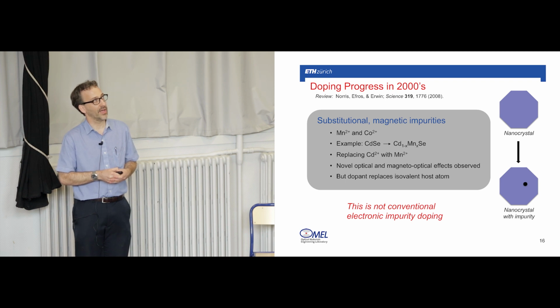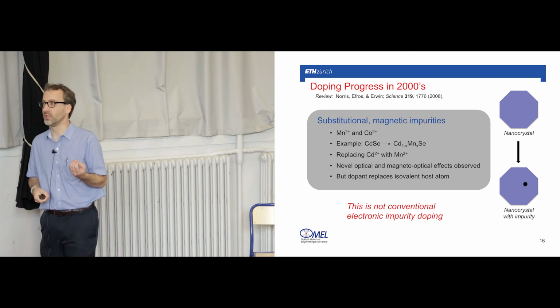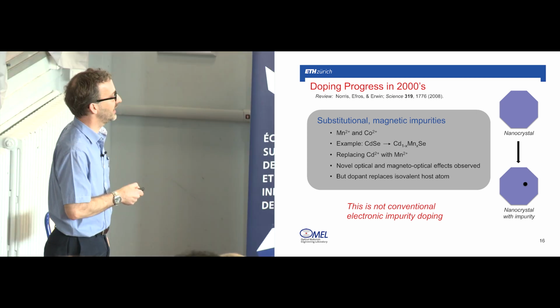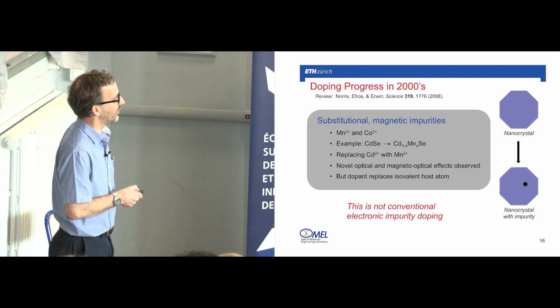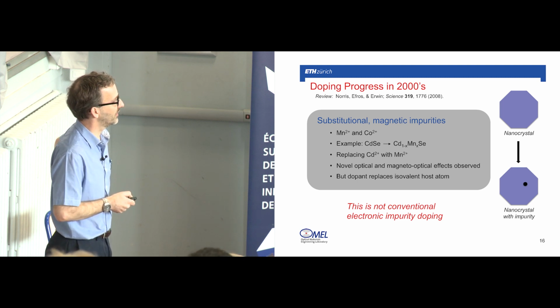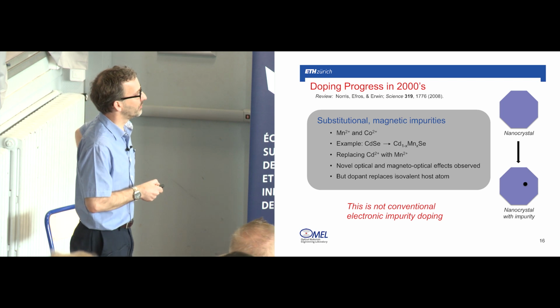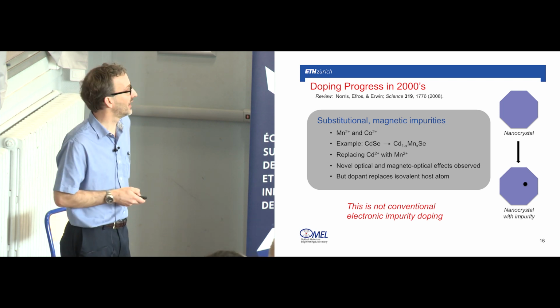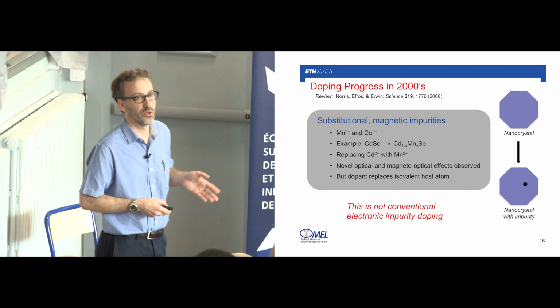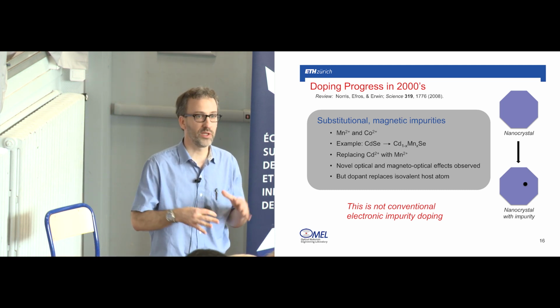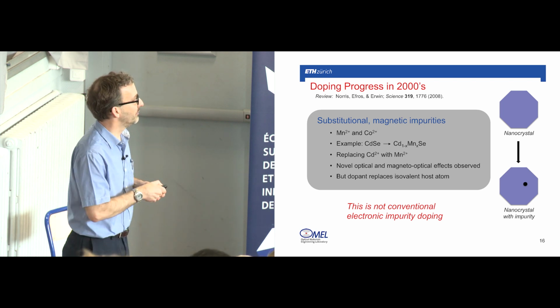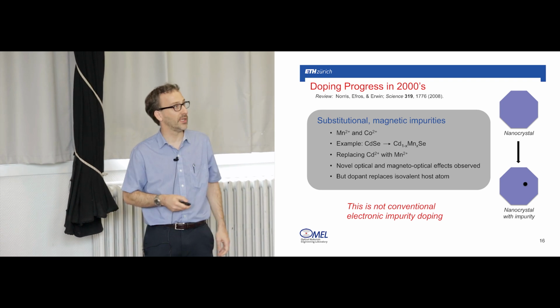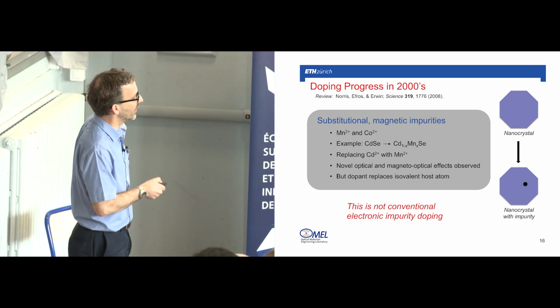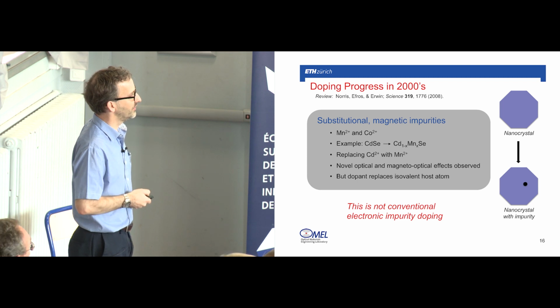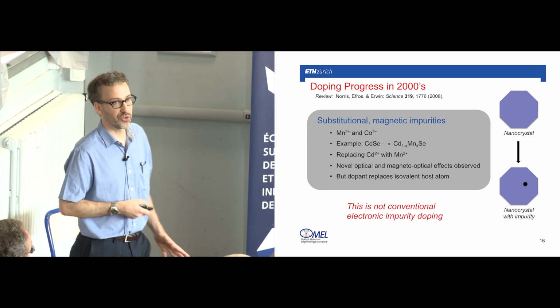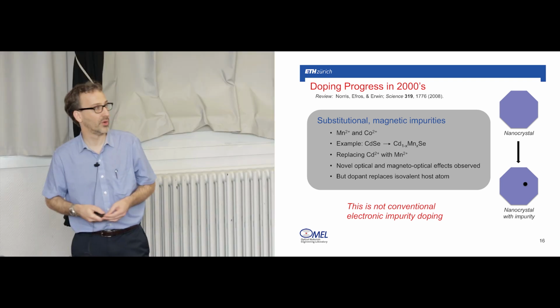Okay, so because of this, there was a lot of progress made in doping in the early 2000s. If we think about it, though, it was all substitutional, or mostly substitutional, and magnetic impurities. Things like manganese and cobalt, like the example I gave of manganese doped into cadmium selenide. Obviously, you're replacing some of the cadmium 2+ with manganese 2+ on the lattice. Although there are lots of interesting optical and magneto-optical properties that have been reported and will continue to be reported about these systems, in particular manganese being both an optical and a magnetic impurity, it's still a dopant that's replacing an isovalent host atom. So if our goal is electronically active impurities, then this isn't going to get us there.